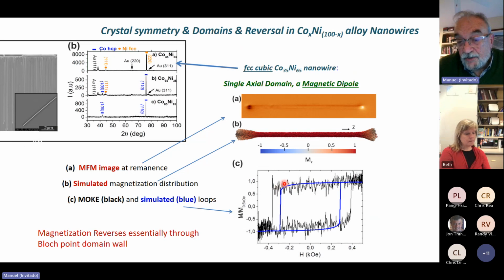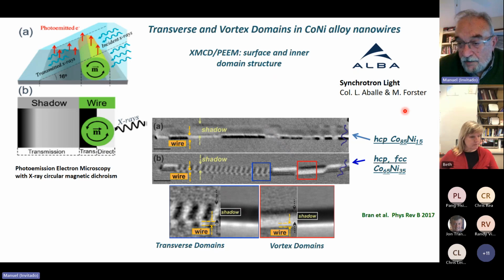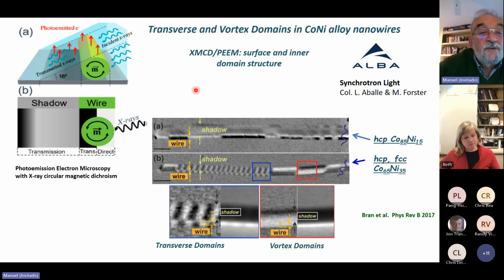Here is the experimental result. The noisy hysteresis loop is the experimental one obtained by magneto-optic Kerr effect, and the blue one is obtained by micromagnetic simulation. But what happens when we change the composition and go to, for example, cobalt 65, nickel 35? Here, we know that in this wire we have some regions with HCP crystal symmetry and others with cubic symmetry. To determine the domain structure in this wire, we have used the synchrotron.